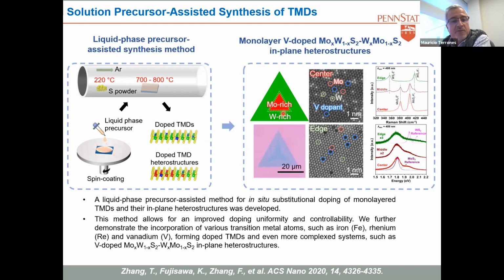chalcogenide. So this is an example of a moly sulfide, tungsten sulfide interface. So in the center, you have moly sulfide rich. On the outside, you have tungsten sulfide rich. And then in the middle, you have vanadium as well, doping this structure. So what you see here at the edge is the Raman of the tungsten rich. So we have these two signals from the tungsten disulfide. You have in the middle the combination of both. And then in the center, you have mainly moly sulfide. And then you have the vanadium atoms that are these ones in blue. So these are very rich systems. It's just to show you the things that we can do.